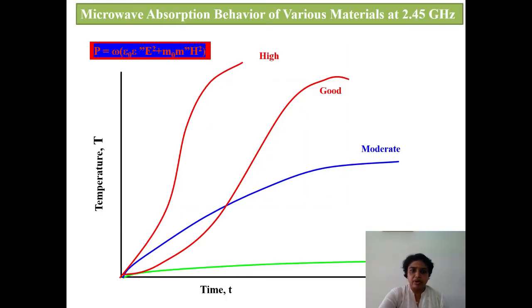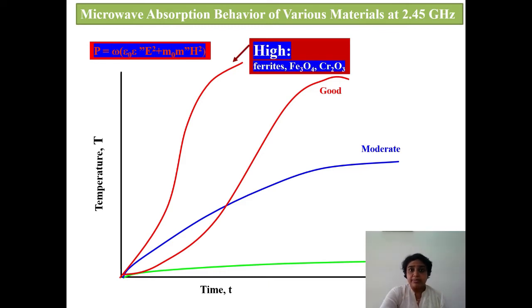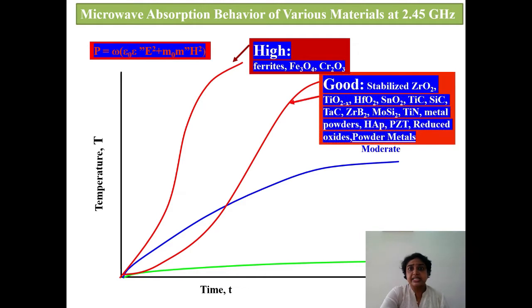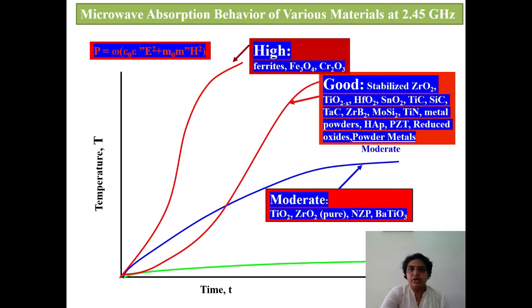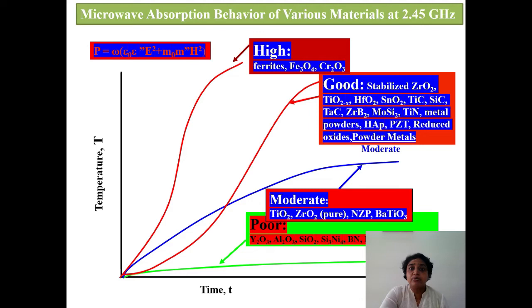Further, if we move forward and look at the microwave absorption behavior of materials at a frequency of 2.45 gigahertz, on the y-axis this quantity P is plotted, that is microwave absorption density, for different materials. First, the high absorbing materials are ferrites, Fe3O4, chromium oxide, because they have magnetic dipoles. The second category is good microwave absorbers: some carbides like silicon carbide, some oxides like zirconia and titanium oxide, then reduced oxides, and some powder metals also. Then the moderate absorbers are pure titanium oxide or zirconia oxide, or titanates also. Then we come to the poor absorbers, which include silica, yttrium oxide, alumina, etc.